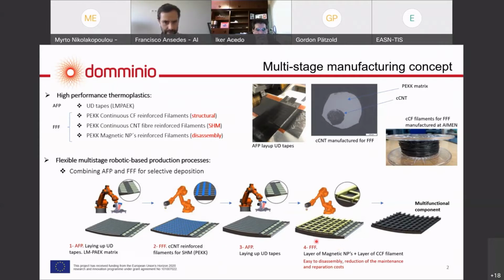So after placing the reinforcements, a grid and a layer of the magnetic nanoparticle filaments are deposited that will allow the disassembly by subjecting them to inductive fields. The magnetic nanoparticles will heat up and melt the polymer matrix in order to allow the disassembly of the reinforcement, which will be placed also by FFF on top of these magnetic nanoparticle filaments, to have a finished multifunctional component.